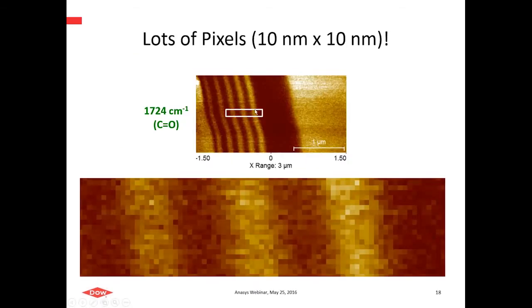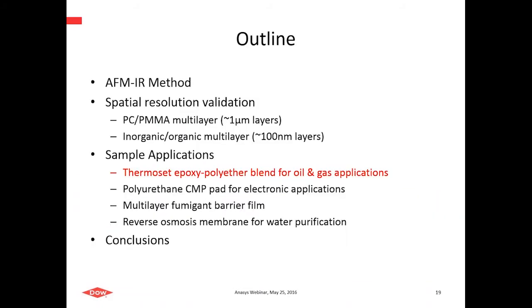And again, it's helpful to zoom in just to convince ourselves we aren't seeing things, in a sense. So we can count about 10 pixels across each layer, and that's at a 10 by 10 nanometer pixel size. That's about 100 nanometers. So we see the modulation in intensity that corresponds to that resolution. So I think we're firmly convinced. We're seeing certainly better than 100 nanometer spatial resolution for the methodologies and systems that we used as test samples.